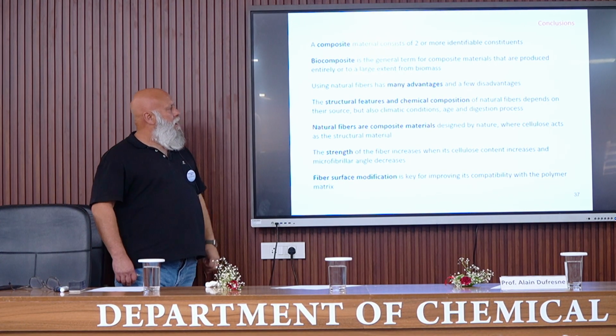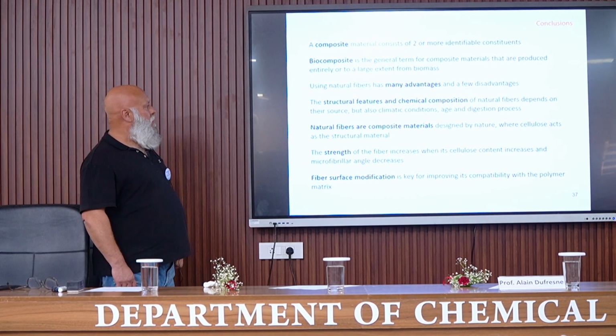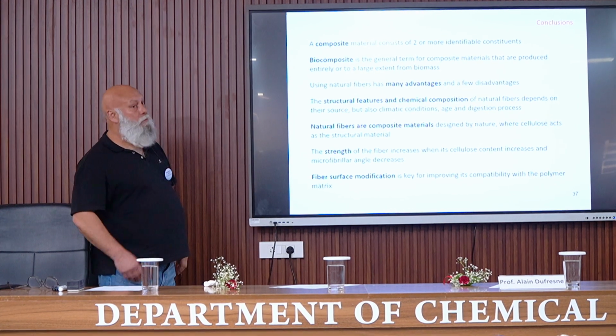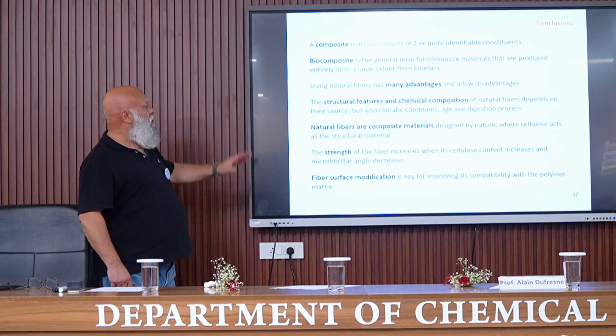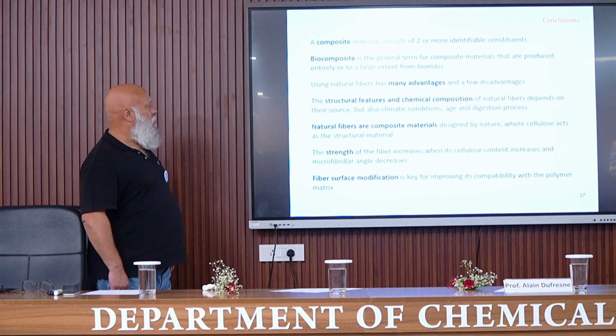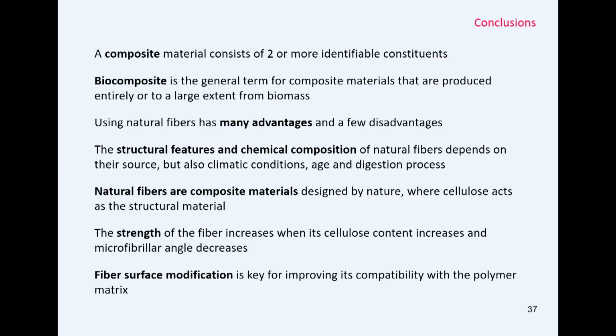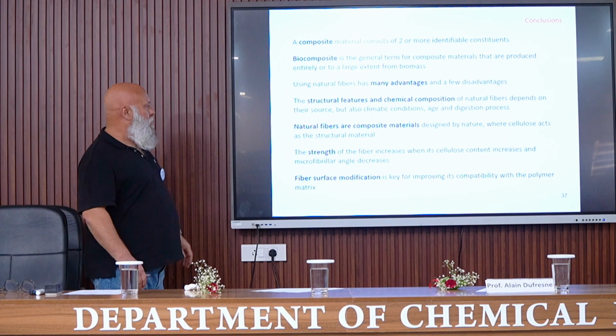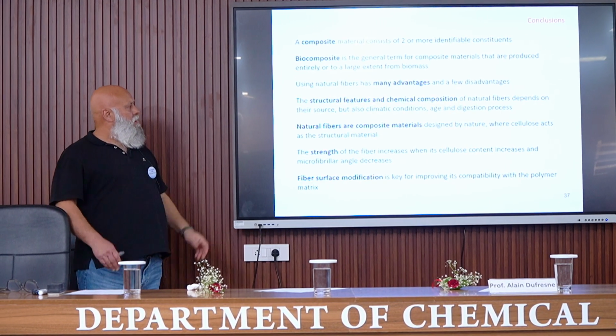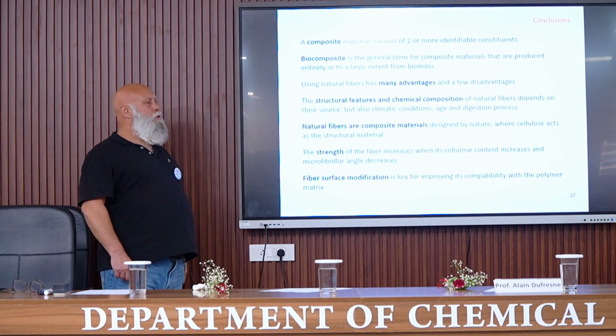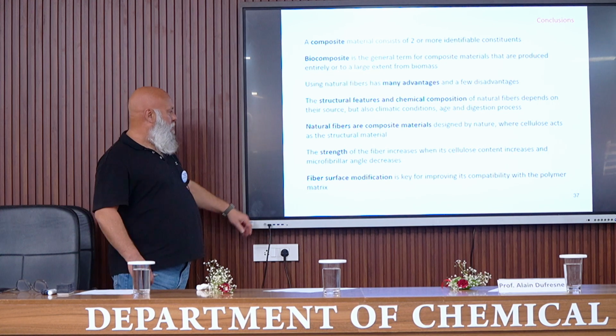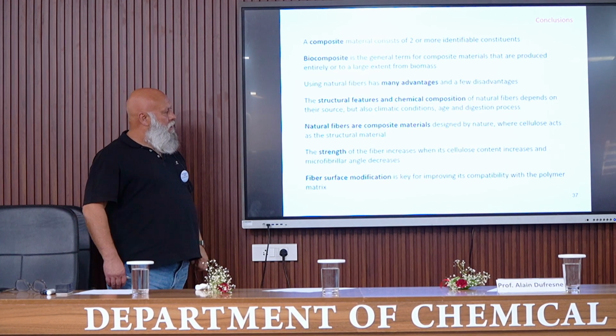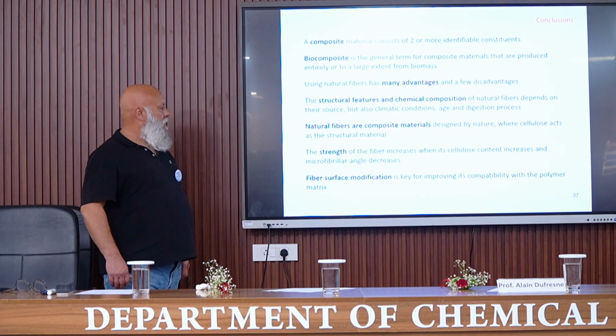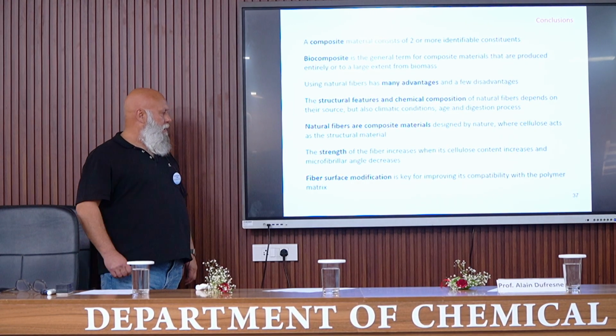The structural features and chemical composition of these natural fibers depend, of course, on the source, or the botanic source of these natural fibers, but also the climatic condition, the age, and the digestion process. All these natural fibers are composite material. They are designed by nature, and we'll see later that it is really optimized in terms of mechanical properties. And in this natural fiber, this composite material, cellulose acts as the structural material, so it provides the mechanical properties. The strength of the fiber increases when the cellulose content increases and when the microfibrillar angle decreases.